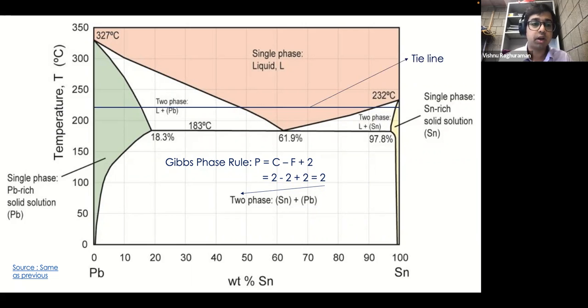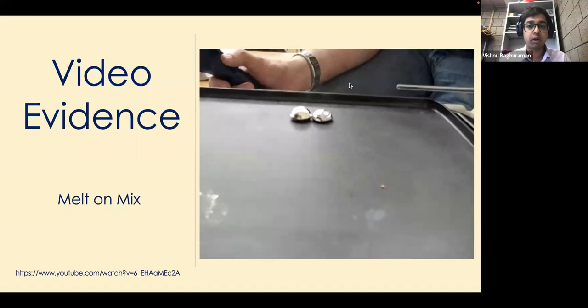And you can study something interesting here at fixed temperature given by this tie line. So you can see that the melting temperatures of lead and tin are quite high. One is at 327 Celsius and one is at 232. But if you mix them, so if you get to 60% weight of tin, you can see that the melting temperature is now much lesser. So it's liquid at a much lesser temperature, which implies that you could have a solid tin, which is hot, and solid lead, which is hot. And then if you put them together, they would mix and they would just melt without you adding additional heat to it. And that is called sort of eutectic behavior.